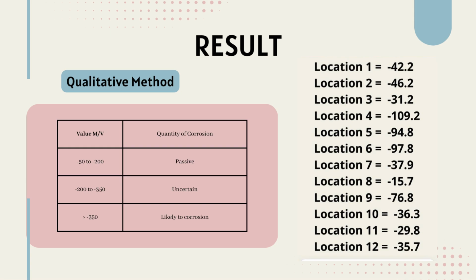So this is the result that we got for 12 locations. Location 1 we got negative 42.2. Location 2 we got negative 46.2. Location 3 negative 31.2. Location 4, the best result we got, 109.2. Location 5 negative 94.8. Location 6 negative 97.8.